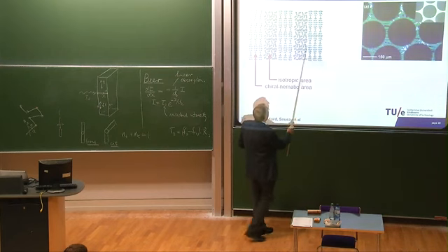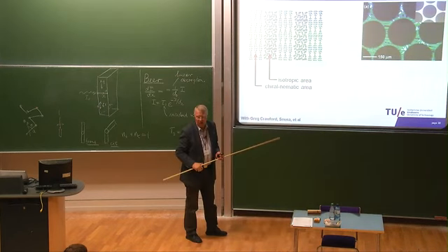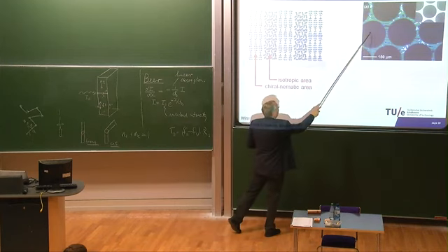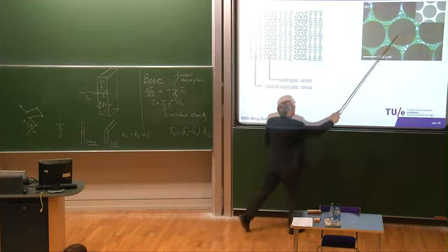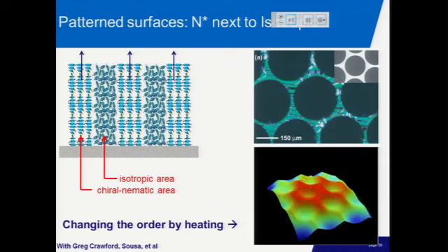These are the green areas here. And we have areas where we have this material polymerized at somewhat higher temperatures, which are isotropic, and between crossed polarizers they are black, and this is the mask that we were using for that. And in this case, we get structures formed like this. So in a sense, these areas go up, and these remain about at the same position.